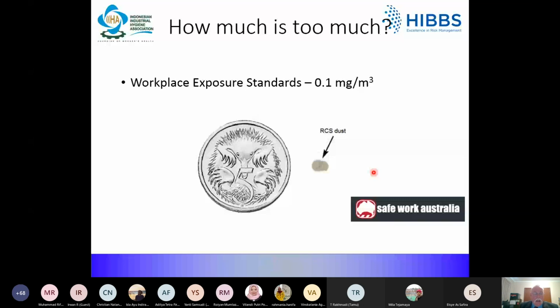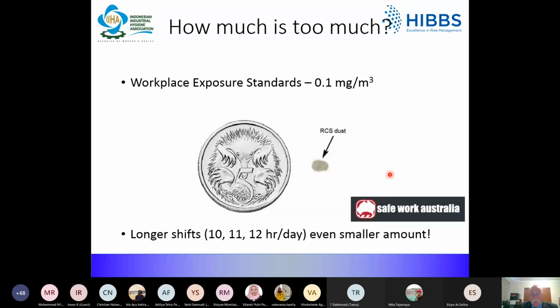Up until last year, the 8-hour time-weighted average workplace exposure standard for respirable crystalline silica in Australia was 0.1 milligrams per cubic metre. Now, the blob to the right of the coin is supposed to represent something in the order of about 0.1 milligrams of dust, which is about the size of a match head. And for extended work shifts, the workplace exposure standard is reduced accordingly to account for the longer period of exposure.